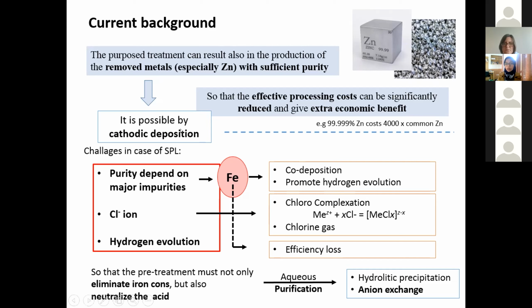With the existence of iron, these conditions get even worse, because iron has a lower overpotential for hydrogen evolution, so it promotes hydrogen evolution, which decreases our efficiency. In another way, this iron also co-deposits with our zinc. So this is our problem.